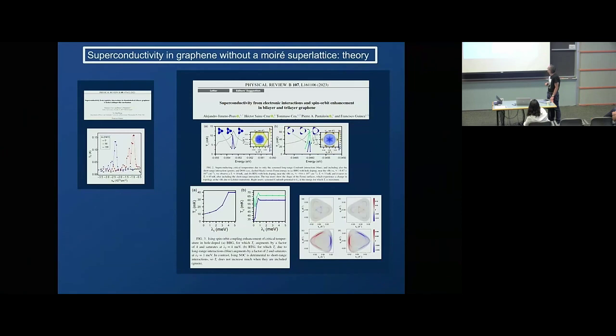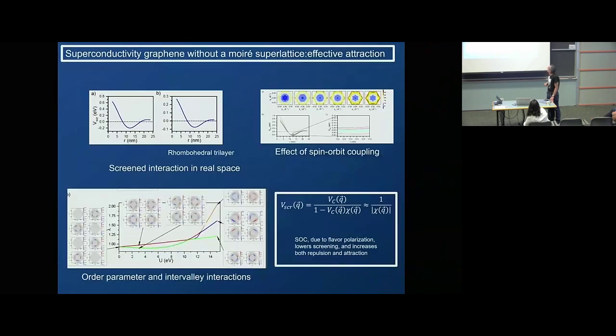And moreover, we played with Ising spin orbit coupling, and we found that the Ising spin orbit coupling enhanced significantly the critical temperature, which is also consistent with experiments.